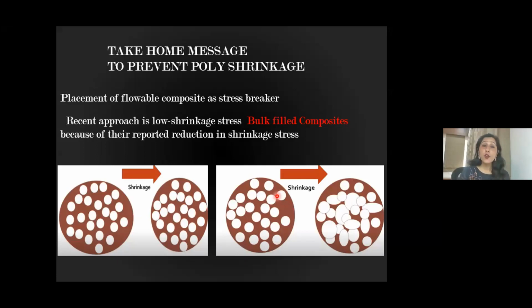Now, placement of flowable composite as a stress breaker. Recent approaches: low shrinkage stress, as I told you that bulk fill composites have such low shrinkage stress because of the reported reduction in shrinkage stress. So use bulk fill composites wherever you feel that the cavity is too deep, is under a lot of stress, comes under stress bearing areas. Use bulk, top it with nano, Money Nano, or use a flowable composite, especially in cervical restorations, so that your composites would serve longer. And these flowable composites of any type are used as a stress breaker.